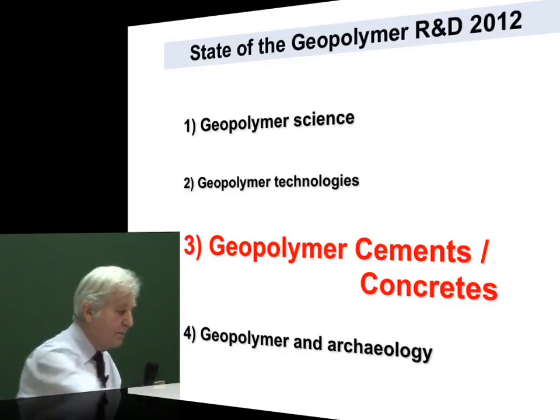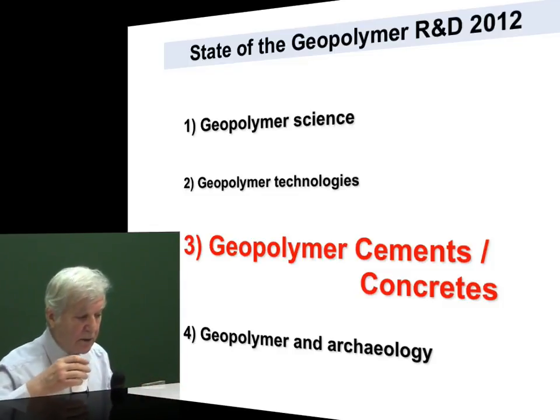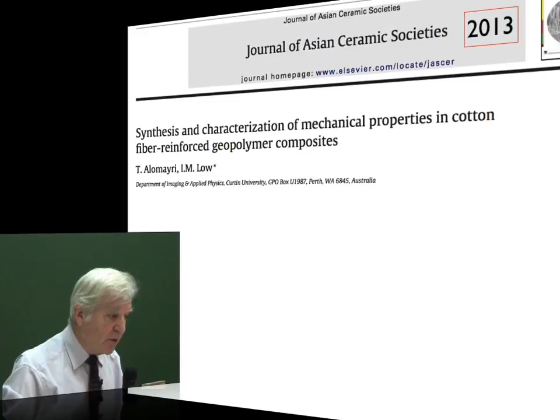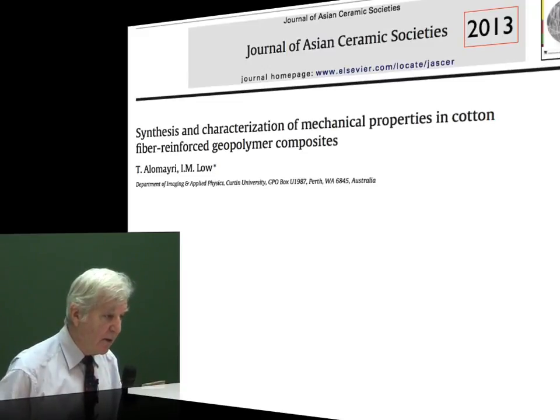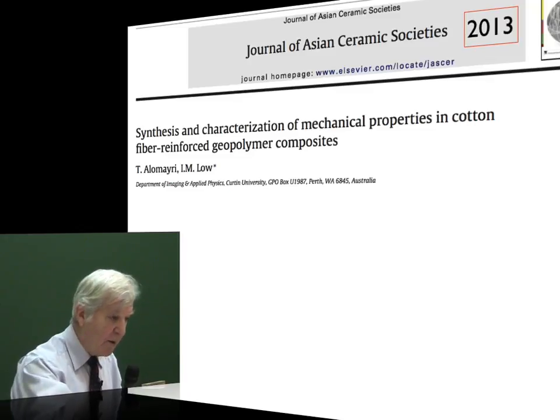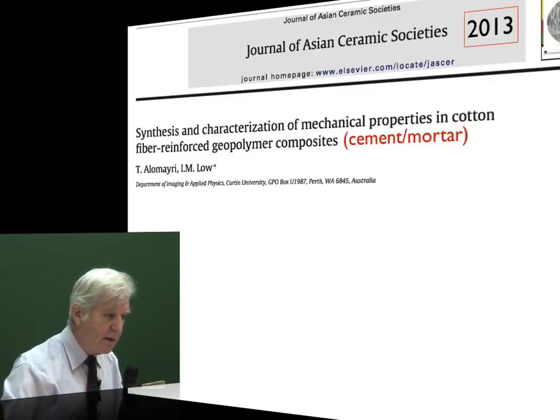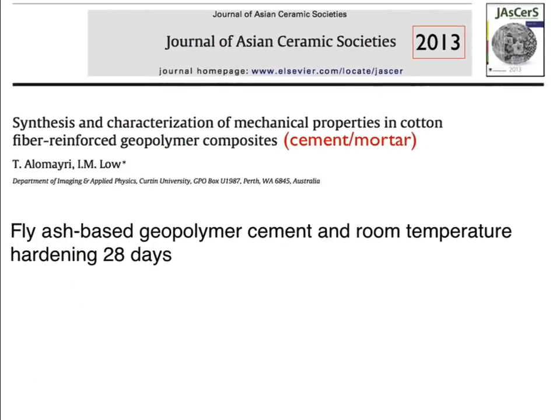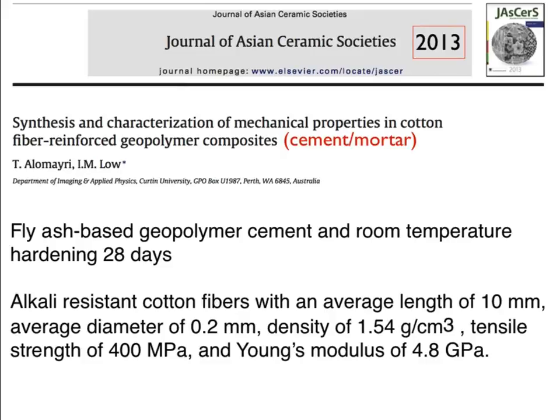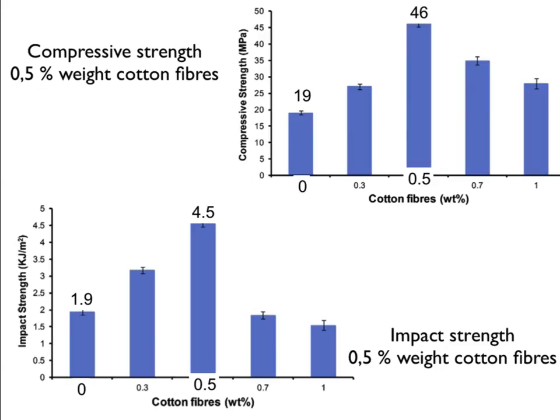We arrive now to geopolymer cement and concrete. Something very unusual. From Australia, synthesis and characterization of mechanical properties in cotton fiber reinforced geopolymer composites. Composite is not the real term, it is cement and mortar. Fly ash-based geopolymer cement and room temperature hardening, this is what they are using. Alkali-resistant cotton fibers with an average length of 10 millimeters, average diameter of 0.2 millimeter, density 1.55 gram per cubic centimeter, tensile strength and so forth. And they see their results.